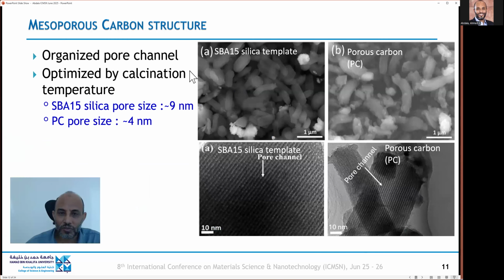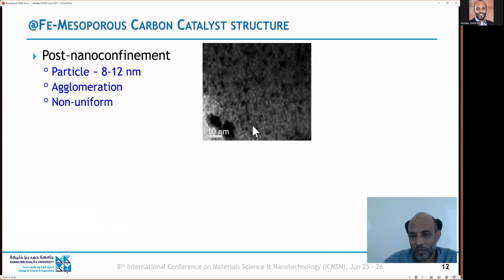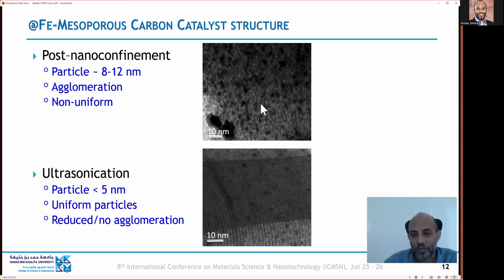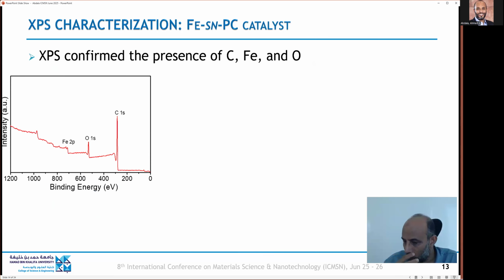If we look at the structure of the catalyst, of course, this is the silica template. You can see the hexagonal shape has a pore size of about 9 nanometers. After formation of the porous carbon material, we get porous carbon channels of about 4 to 5 nanometers. And then with the catalyst supported on the porous carbon, you can see if we do it with the post-confinement technique, we get particles of about 10 nanometers on average, but there is a lot of agglomeration, as you can see, in multiple places. The distribution is not excellent. On the other hand, if we do the sonication-assisted approach, we get a smaller particle size, for the most part maybe about 5 nanometers, no significant agglomeration, and better dispersion of the iron nanoparticles.